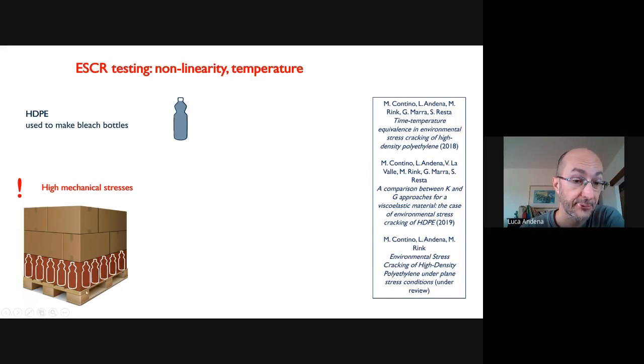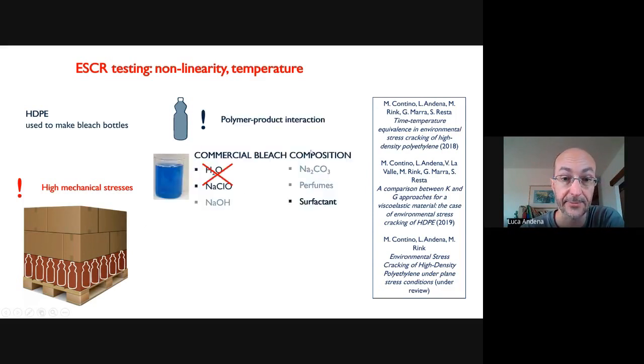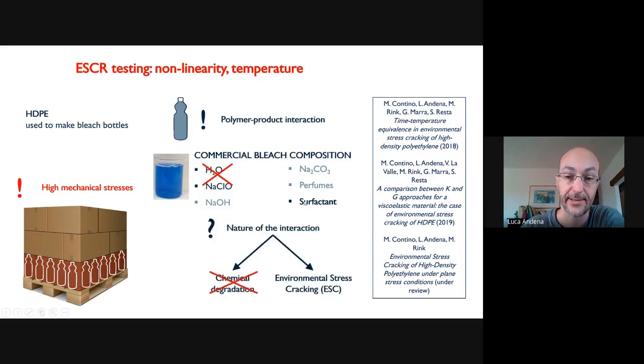The problem here is storage, when the bottles at the bottom suffer from the load of the stacks of the ones stacked above. Here, the problem is not bleach itself. The material is chosen to be resistant, but commercial bleach includes surfactants, which are a well-known ESC agent for polyethylene. Here, the effects that we will consider will be nonlinearity and temperature.